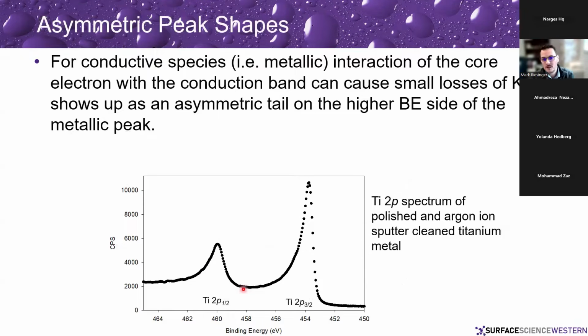For conductive species such as metals and graphite and those sorts of things, you can get interaction of the core electrons with the conduction band, and these will cause small losses of energy that show up as an asymmetric tail on the higher binding energy side of the metallic peak. So for something like, say, a titanium metal sample that's been sputter cleaned and polished and all that sort of stuff, so it's very pure metal, this peak shape is no longer that nice Gaussian-Lorentzian peak shape. It's now an asymmetric shape.